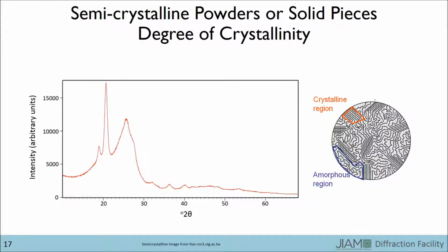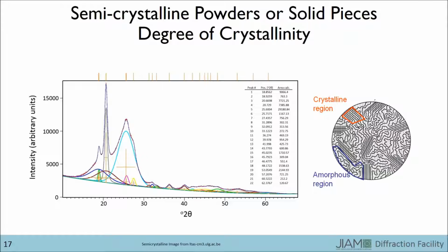To this point, we have looked only at crystalline materials. The images shown here, however, correspond to semi-crystalline materials. The diffraction patterns of semi-crystalline materials have sharp crystalline peaks along with broad amorphous peaks. Determining the degree of crystallinity of such a semi-crystalline material requires first deconvoluting the diffraction pattern. For instance, an example of the raw data is shown in the figure. This pattern is a sum of all peaks. Utilizing software such as HighScore Plus or Origin, we are able to determine the contribution from each peak. Such analysis should also give the area beneath each peak, which can then be used to calculate the degree of crystallinity by dividing the total area of the crystalline peaks by the total area beneath all peaks.